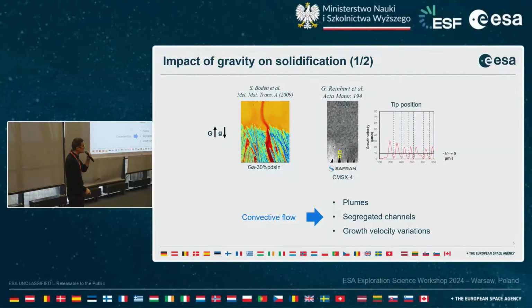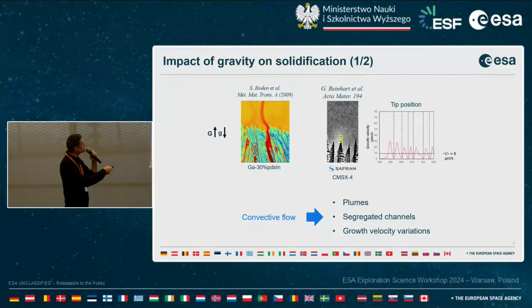This was in a model gallium-indium alloy. It's nice to see that we observed the same in a commercial alloy, CMSX-4. You can see here in this video the solute plumes drifting from the right to the left, and you can see how it impacts the growth and the velocity of the dendrites. So it has a major impact on the development of the solidification microstructure. So you have plume segregated channels and growth velocity variations.